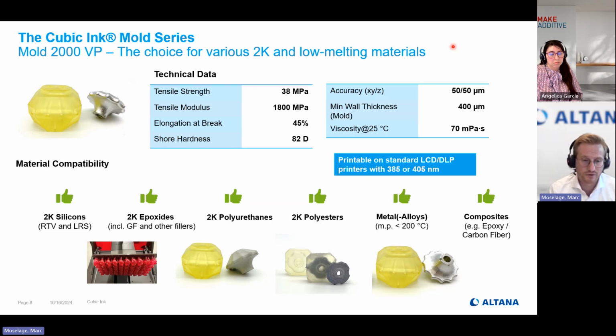It additionally works fine for a couple of other 2K materials, such as 2K epoxide, including fillers, 2K polyurethanes, and polyesters. It works also for metal alloys, which is shown on this image here up left. I should say this is not stainless steel or aluminum. This is not feasible. It is a low melting alloy. This one shown is called the Field's metal. It is an alloy consisting of indium, bismuth, and tin, with a melting point of roughly 70 degrees centigrade. So relatively low melting, and something we can do well in our lab. Low melting alloys with a melting point of circa 200 degrees work fine.